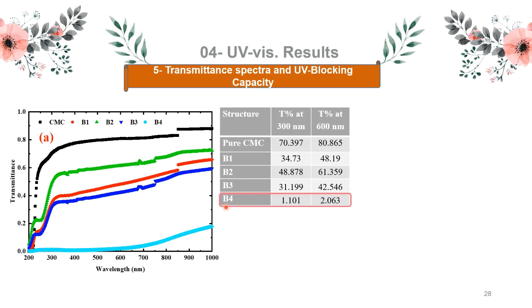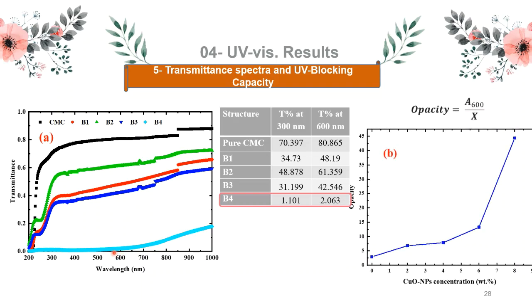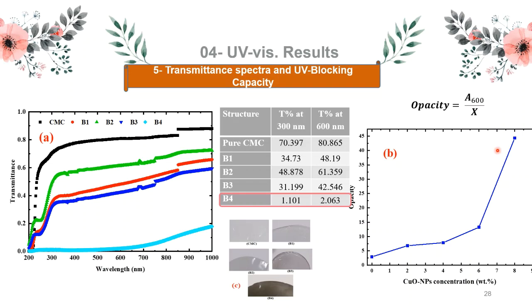This means that this sample was discovered to be the optimal percentage for successfully blocking UV radiation, as it extends to the UVA, UVB, UVC, and also to the visible region. The relationship between opacity and copper oxide concentration was determined using this equation. We can see that a higher opacity number indicates a lower transparency of a film. A visualization of the CMC and nanocomposite films was also made and reveals that their color gradually changes from transparent to relatively dark gray and finally to black, with the CMC film being more transparent, with a lower opacity value.